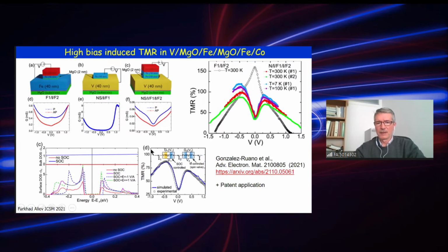This effect, briefly mentioned, the huge change of conductance of this vanadium MgO iron system under applied bias gives rise to the very amazing effect of very high TMR at high biases. So basically in the control system, the iron MgO iron, the low bias TMR is bigger, but above 0.5 volts, the tunneling magnetic resistance in these structures can be much higher than in standard structures. We published this recently, and we also have a patent application for these structures.